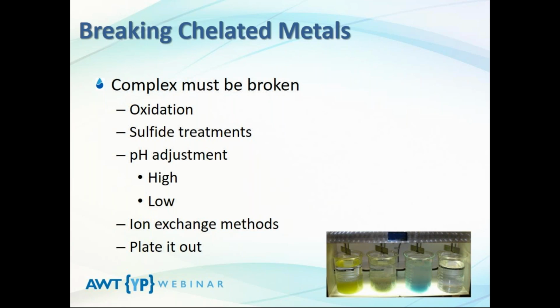I will simply plate that copper onto steel wool and onto powdered steel and sell that copper to a copper scrap dealer. It's worth a lot of money, and lately copper prices have really taken off again. That's called a plate out. You can also do that with nickel as well. Let's say you're going into that bath at 100 ppm copper. You can plate that out to where the soluble copper residual is 5 ppm or less. And we do that with success.